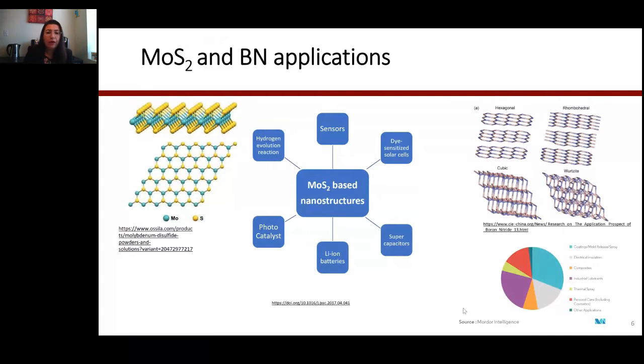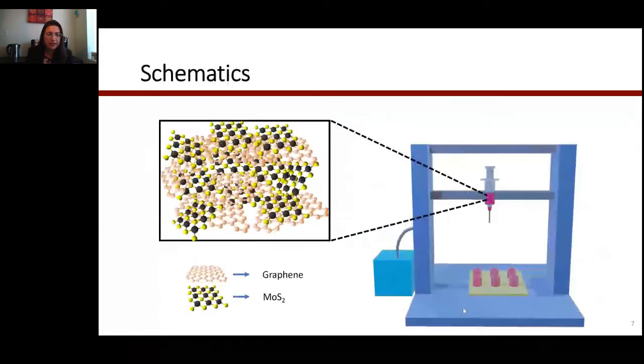So how do we actually do that? We needed 3D printers and all of that, and we didn't have any of that. We didn't have money for that either. Part of Grow was that they could pay for me to go to France, to a professor there. He modified a 3D printer to 3D print with a syringe. So we made the gel, we mixed the graphene and MoS2, and we 3D printed that.